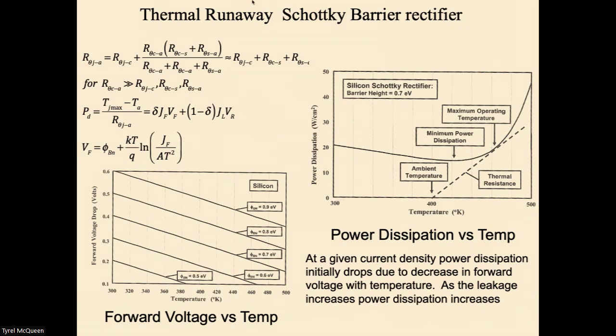So what happens as the Schottky barrier rectifier, which is this case, heats up? As it heats up, initially the power dissipation is going to go down because the on voltage will decrease as the temperature increases. So the power dissipation will go down initially. However, at some point, leakage currents in the Schottky barrier diode become high enough so that the power increases, and the current density times the on resistance also begins to cause the power dissipation. So at some point, there will be a turn